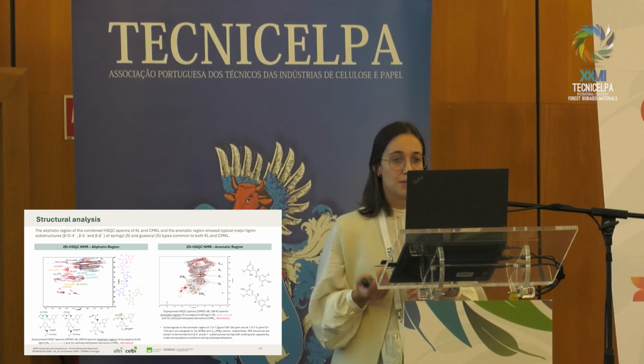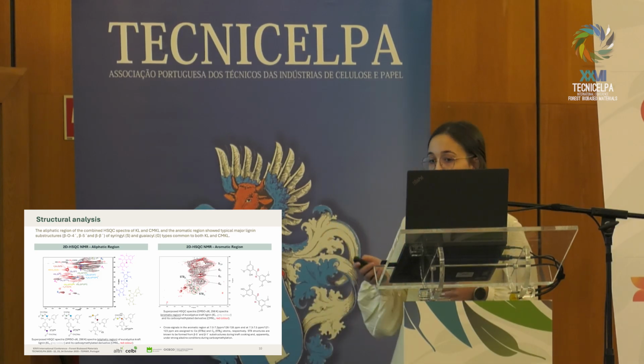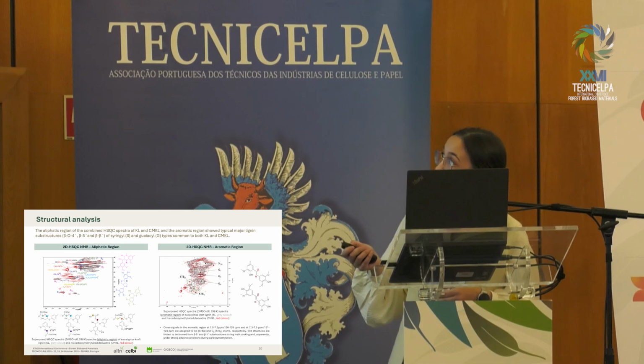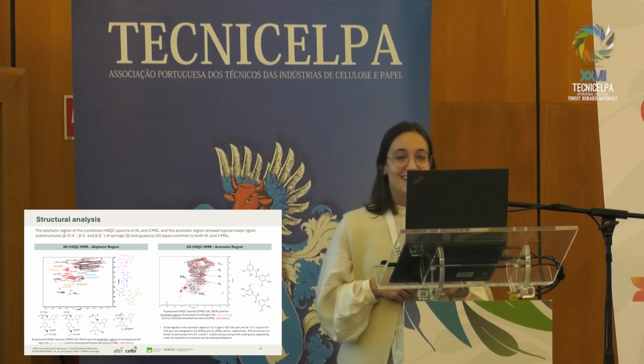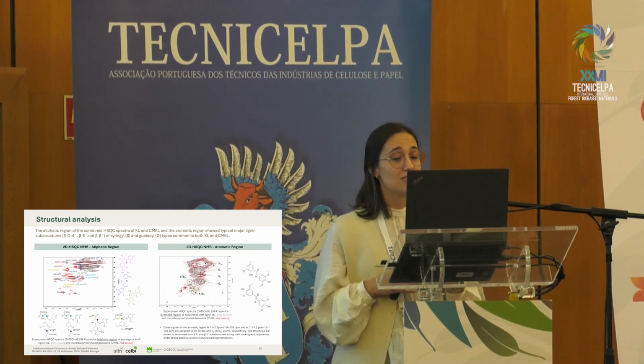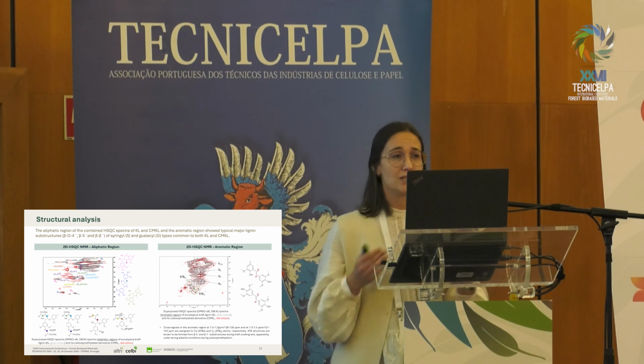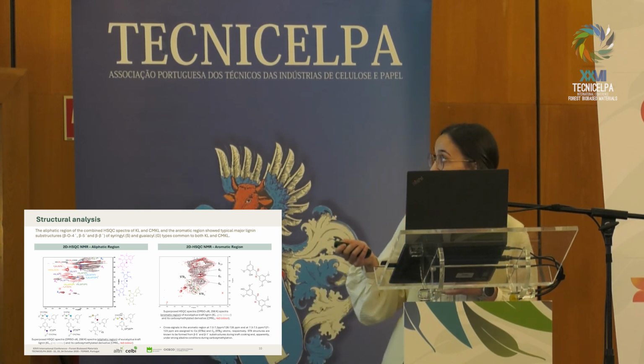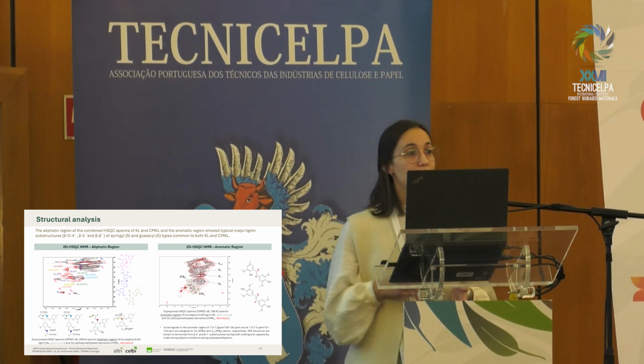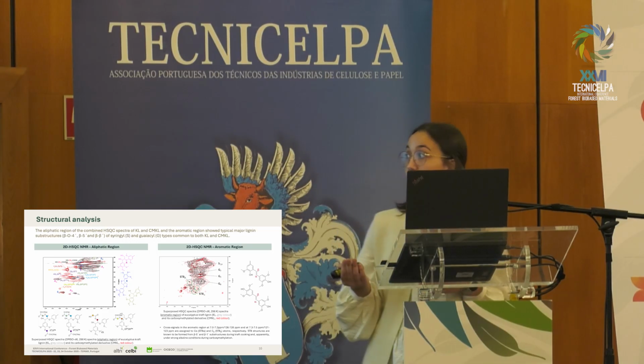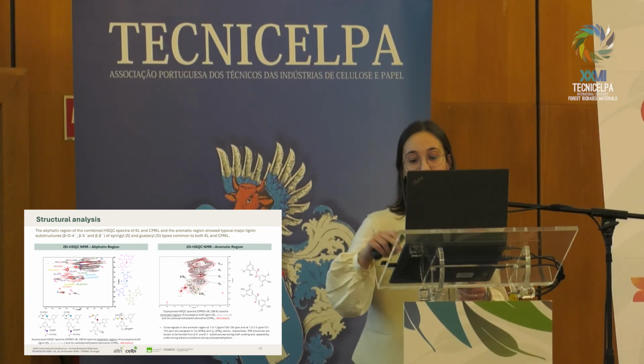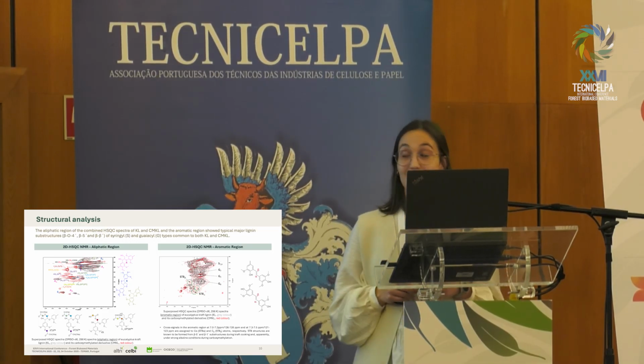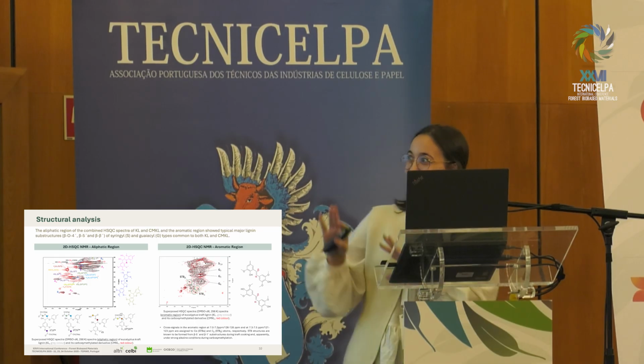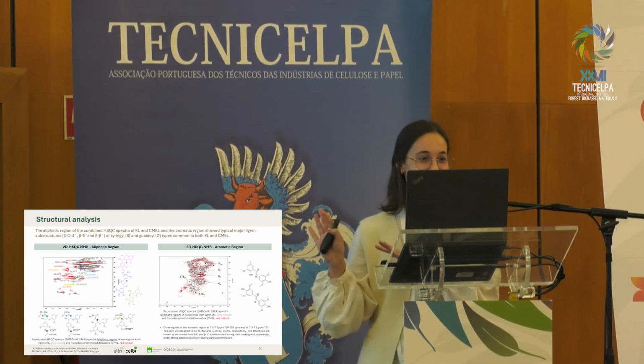Regarding the carbon NMR, new signals from carboxyl and methylene carbons appear at this yellow and green band. And we also see an increase in the resonance at 152 ppm in here, which confirms the etherification of phenolic hydroxyl groups during the carboxymethylation process. So, this seems complex, but it's not.